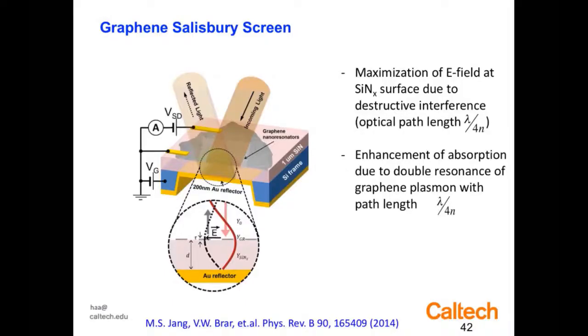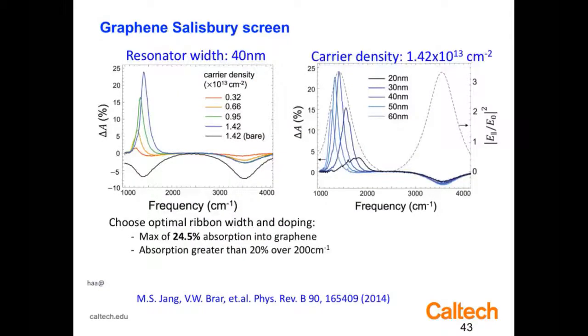So to enhance the absorption, we use an effect that was first recognized in the microwave field, which was how to make surfaces of metals be perfectly absorbing. And the answer, of course, is very simple. It's to match the impedance of the metal to the impedance of free space. And that's how an electrical engineer would think about it. But the wave optical way to think about it is light comes in, scatters from these graphene resonators. If I put a mirror behind it, part of the light transmits through and reflects from the mirror. If I get cancellation of the light reflected from the mirror from the light reflected from the graphene, I'd get 100% absorption. So that was an interesting idea. We tried that, and we were able to get the absorption up from 2% to about 25%. That's fairly impressive for a submonolayer thickness sheet of graphene by changing the carrier density, but it still wasn't 100%.